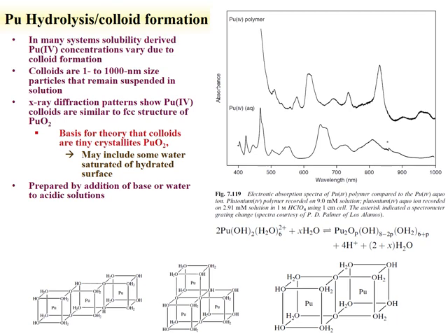One of the consequences of the strong hydrolysis of tetravalent plutonium is the formation of colloids in solution. As we saw in the colored test tube solutions, the plutonium-4 polymer is a different color, and the UV-Vis data also shows a different result. Here, plutonium-4 colloids have a higher absorbance at the lower wavelengths under the conditions examined, whereas plutonium-4 in solution just shows a characteristic absorbance peak at around 475.